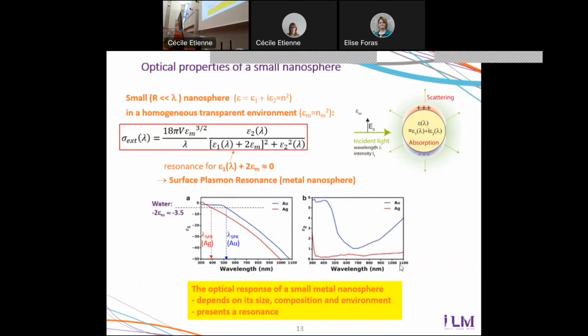Okay, and this condition for resonance, you see it has one term, the real part of the dielectric function of the particle itself, so something related to the composition of the particle, and here something related to the composition of the environment. So again, it depends on both compositions, and in particular, it will not be the same depending on whether you have, for instance, a silver nanoparticle or a gold nanoparticle. The resonance condition will occur at different wavelengths.